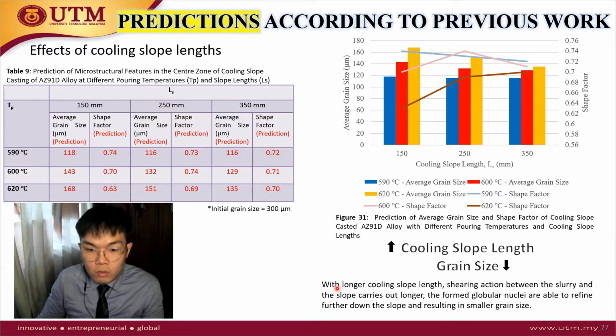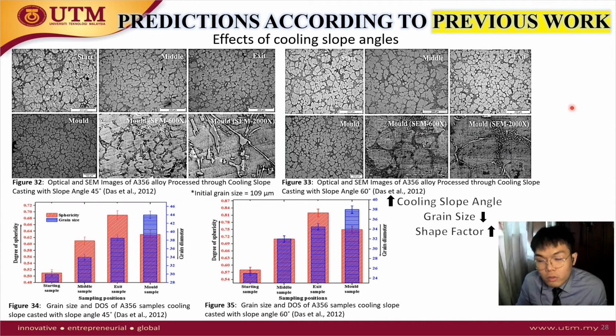And with longer cooling, this is because the shearing action between the slurry and the slope carries out longer. The formed globular nuclei are able to refine further down the slope, resulting in smaller grain size. And we move on to the third cooling slope casting parameter, the cooling slope angle.